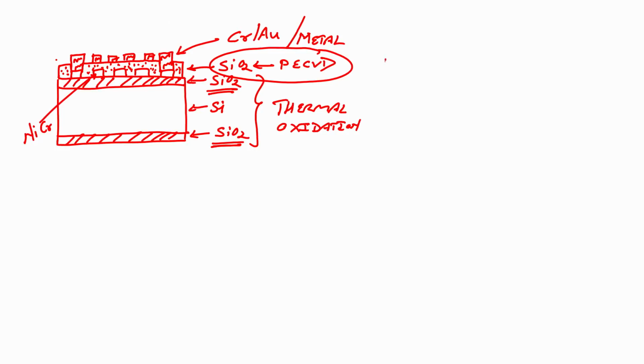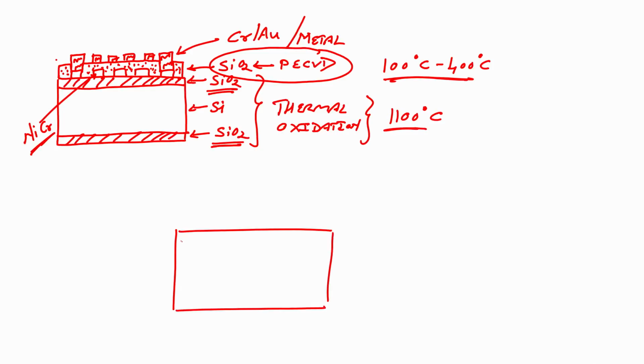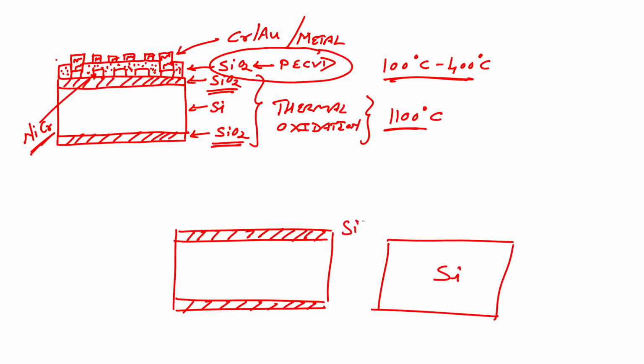You see, in PECVD, we can vary the temperature from 100 degree centigrade to 400 degree centigrade for the chemical vapor deposition. For thermal oxidation, the temperature is 1100 degree centigrade. Again you can vary from 1000 to 1200, generally it is 1100 degree centigrade. Okay. Now, you have nichrome. So, I will just draw quickly a heater on an oxidized silicon wafer, right. Please understand the term: this is a silicon wafer. When you grow silicon dioxide on a silicon wafer, it becomes an oxidized silicon wafer, all right. So, on the oxidized silicon wafer, we are fabricating a micro heater, right.